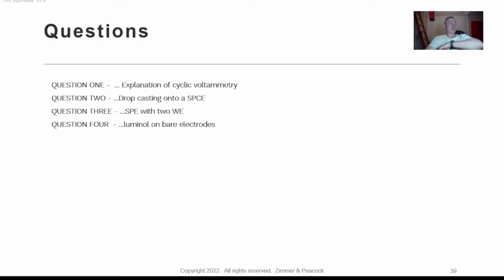Luminol on bare electrodes. Yes, you have put a polymer on those electrodes. You can see it going from the graphite to the graphene, and thank you for finally somebody helping to demonstrate that graphene is not the magic material when it comes to biosensors. But then you have put that polyluminol down, and it's not then able to exchange electrons with the ferrocyanide, and that's why you have a big charge transfer resistance, and then you lose all your activity in the cyclic voltammetry.